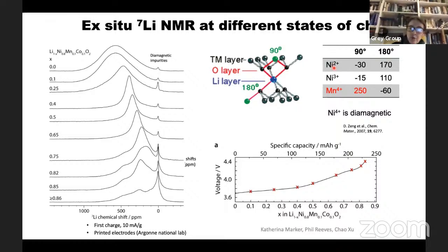And so, for example, if you have nickel 2 plus, nickel 2 plus is D8, so there are electrons in the EG orbitals, and they point towards the lithium. And it's not as simple as all the electrons just sitting on the nickel orbital. If you have a covalent bond, some of them are transferred from the nickel through the lithium. And it's these transferred electrons, through bonds and also through space, that are responsible for magnetic couplings and for magnetism. But we're operating in the regime where things are paramagnetic, but you still have the effect of the unpaired electrons.